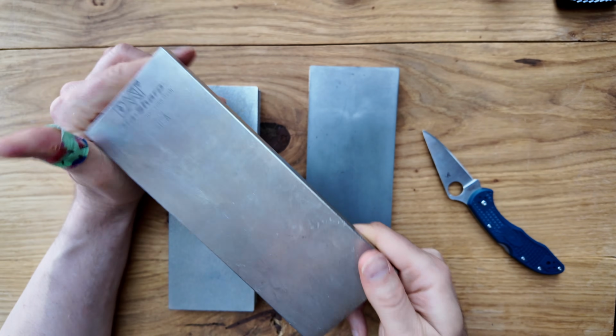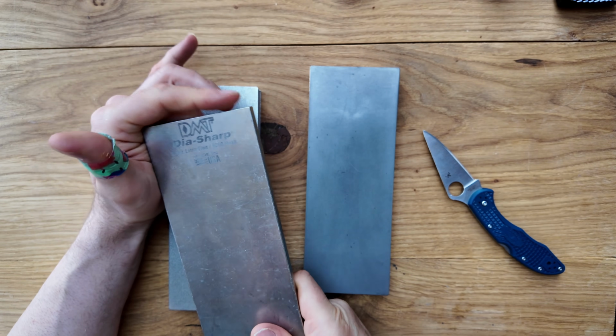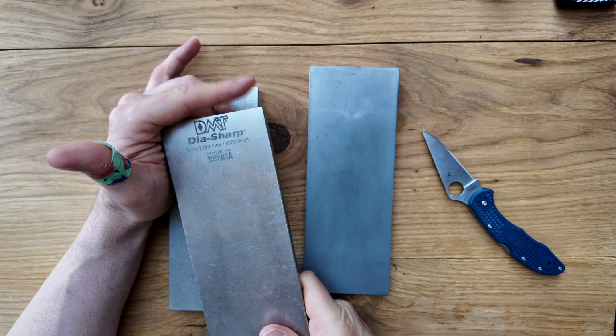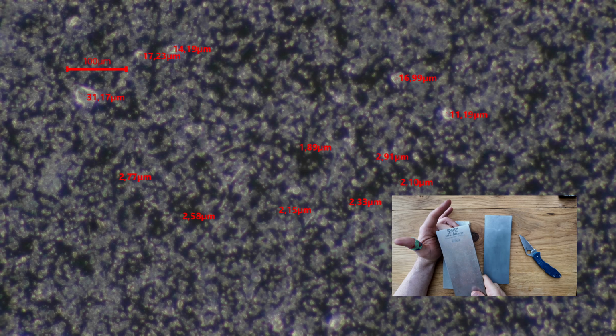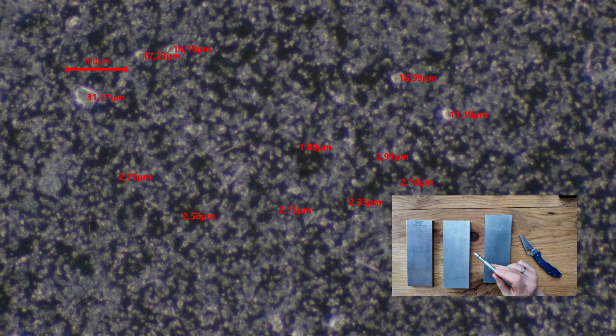The 8000. So normal grain size for the 8000 is roughly 1 to 3 microns. The fine grains on this stone measure between 1.9 and 2.9 microns. That is exactly where an 8000 grit diamond stone should be. The clustering is tight. But there are also some outliers. So there's an 11, 14 micron, 17 micron, another 17 micron, and then even one at 31 microns.